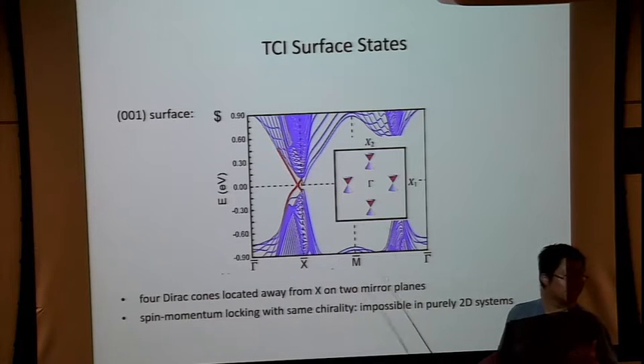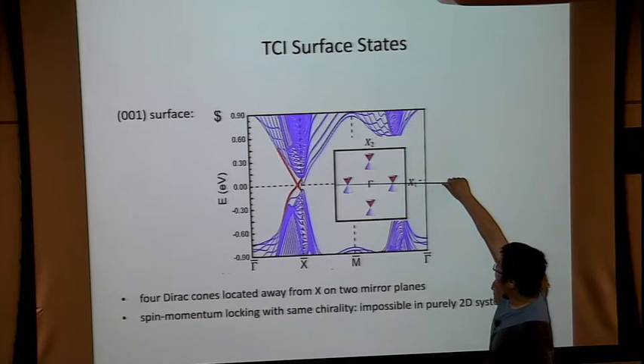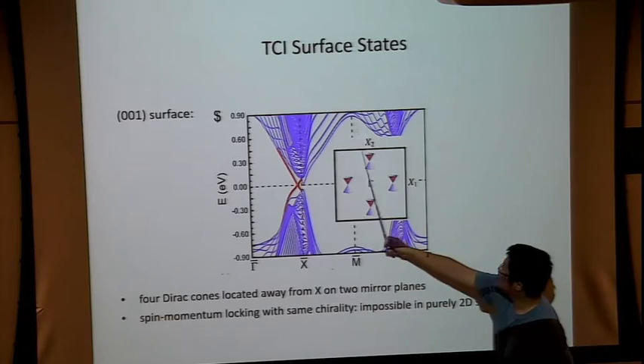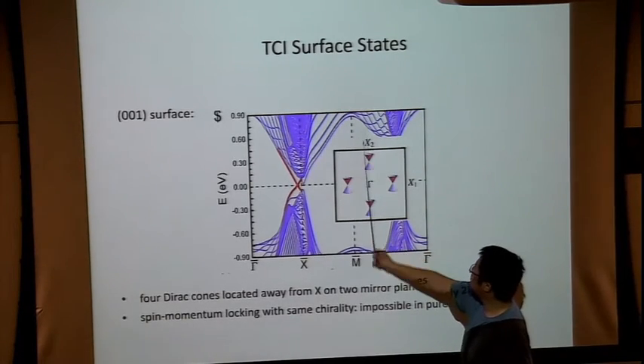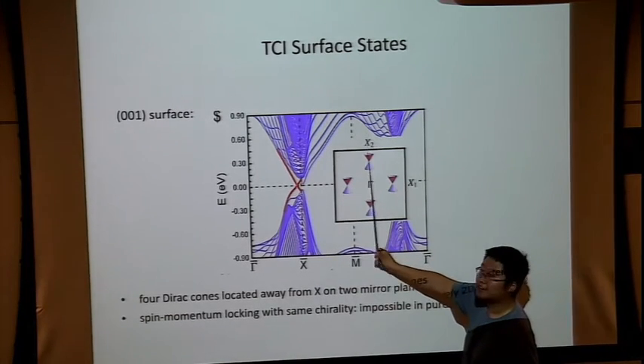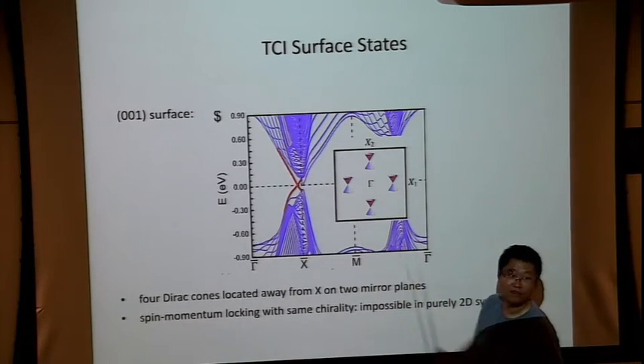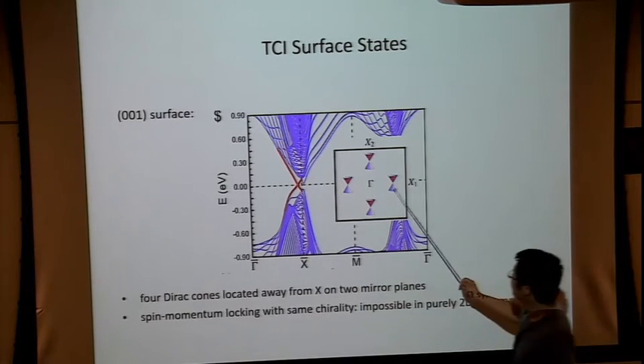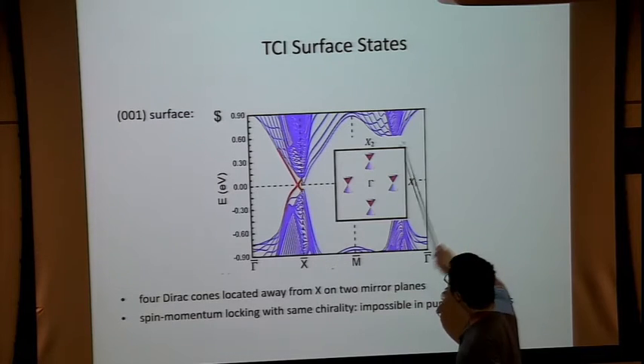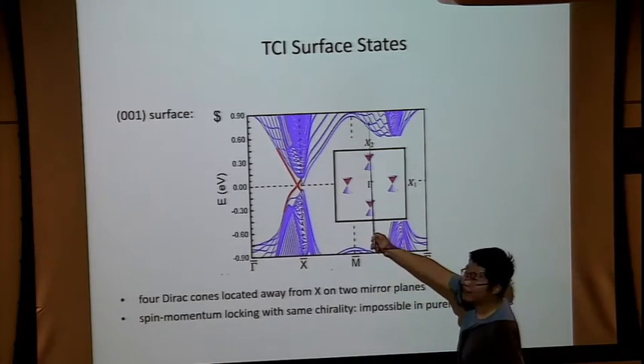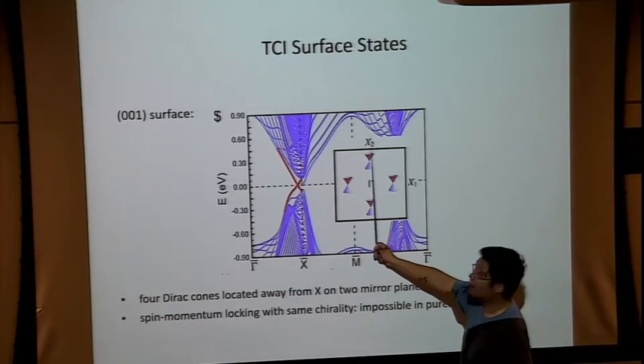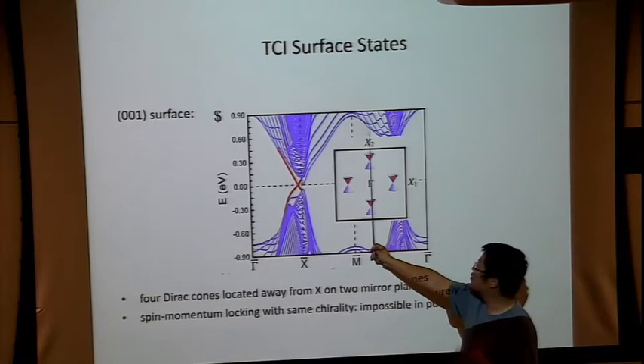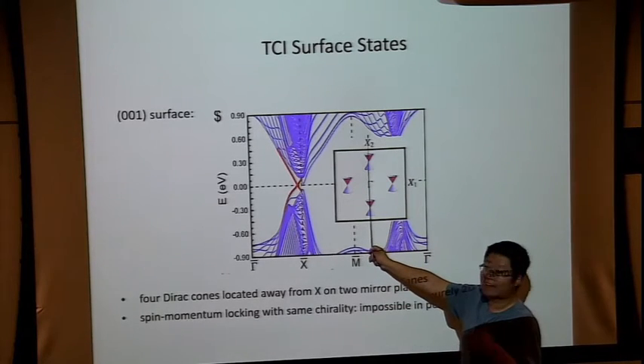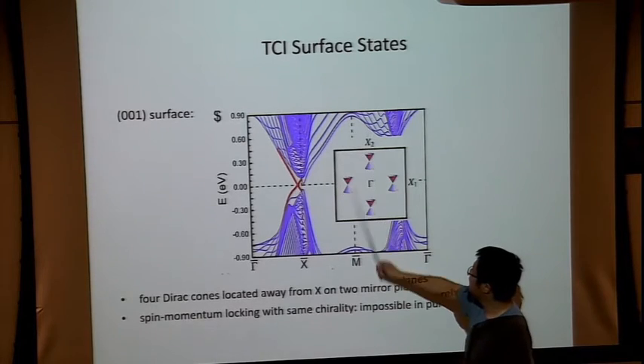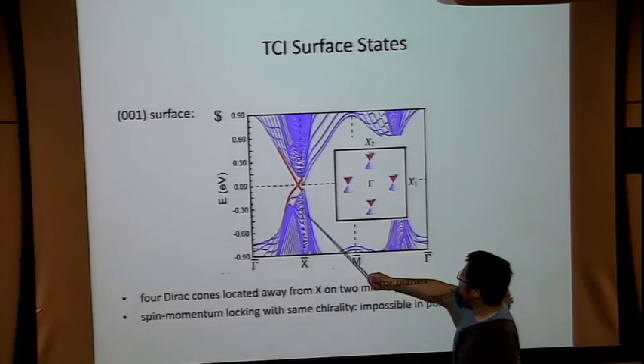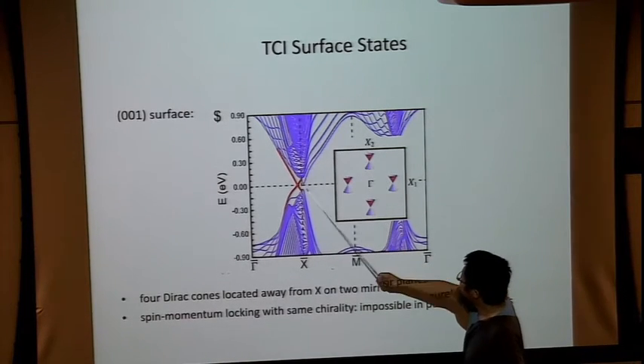In fact, if we break time-reversal symmetry, these Dirac cones are still present. They are located instead on the reflection invariant planes. For example, this line is invariant under x going to minus x. So the Dirac points are forced by reflection symmetry to lie on this plane. They can move smoothly along this line, but not away from it when mirror symmetry is present. One way you can see that these Dirac cones have to be present is to take a cut. For example, look at this particular line, kx equals 0, and look at the dispersion as a function of ky. We know that there is a mirror Chern number associated with the two-dimensional band structure on this kx equals 0 plane. The mirror Chern number being 2 guarantees that on this line there have to be 2 modes moving to the right and 2 modes moving to the left. So this is exactly what is causing the crossing here.